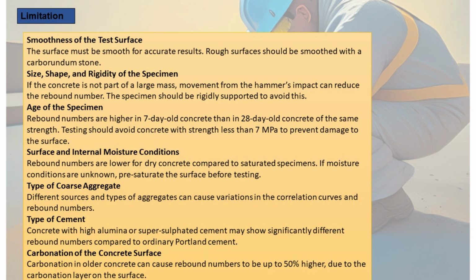The moisture condition of the concrete affects the readings. Drier concrete gives lower numbers. Additionally, different aggregates and cement types, such as high alumina or supersulfated cement, can cause variations. Lastly, carbonation in older concrete may result in rebound numbers up to 50% higher than for uncarbonated surfaces, affecting accuracy.